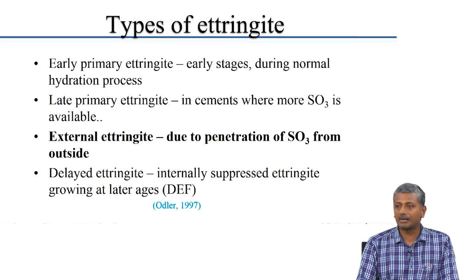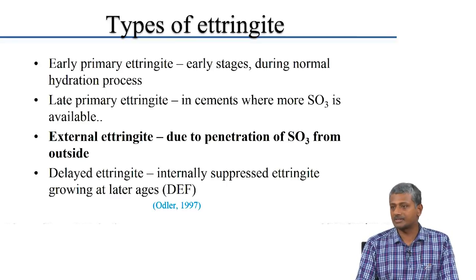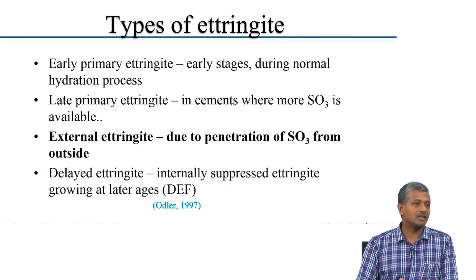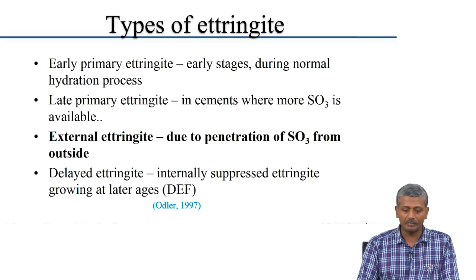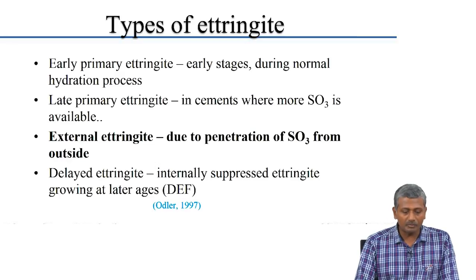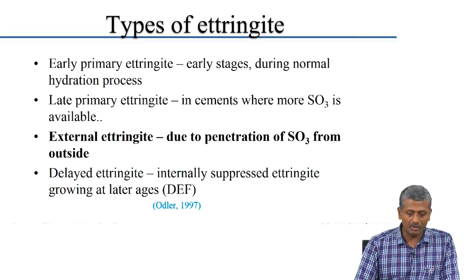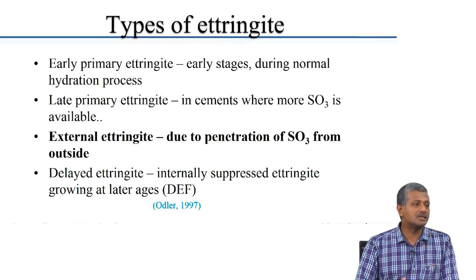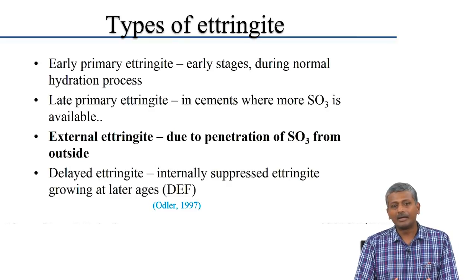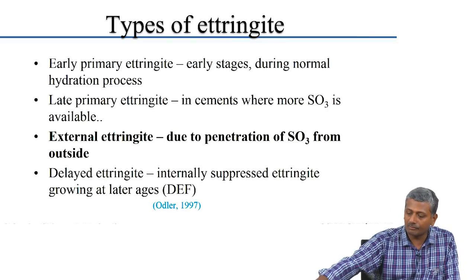There is also evidence of late primary ettringite forming in cements where more sulphate is available, so ettringite continues to deposit for a fairly long period. This happens because of internal sources of sulphates. External ettringite is when sulphates come in from external environments due to penetration from outside. Delayed ettringite formation (DEF) refers to internally suppressed ettringite that grows at later ages — because of some reasons ettringite did not form at early stages, and a combination of factors led it to form in a hardened state. When an expansive material forms inside hardened concrete, that is when major damage occurs.